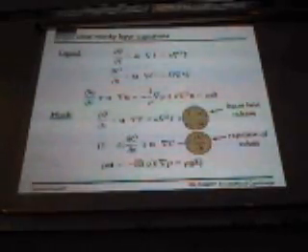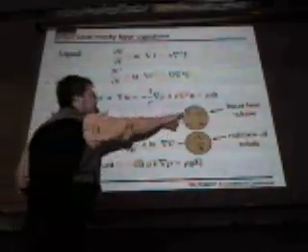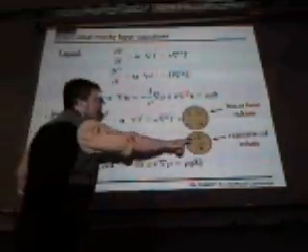And the equations that describe this, averaged over several of those interdendrite spacings, are as follows. In the liquid above, you're really looking at advection and diffusion of both heat and concentration, and the Navier-Stokes equation describing momentum. In the mushy layer below, you have advection and diffusion of heat, but now you have to worry about the fact that the phase fraction can change throughout this mushy region, and so there can be release of latent heat internally as you change the phase fraction. Similarly, you have an equation conserving solute where I've neglected diffusion, as is typically done because the length scale there is so small. But again, you need to worry about the release of solute as you change the phase fraction within this porous medium. And then velocity is governed by Darcy's law.